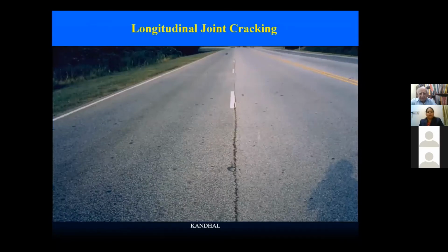Let's say I have this lane and this lane. Say the paver went on this lane first, so I did not have any confinement on this side. So I got a very low density at the edge of this pavement. Then when the paver came around and paved this lane, there was a confinement here, so I got a good density on this side. So there's a density gradient here. I got a low density on this side of the construction joint and a high density on this side, and because of that, this joint opens up.